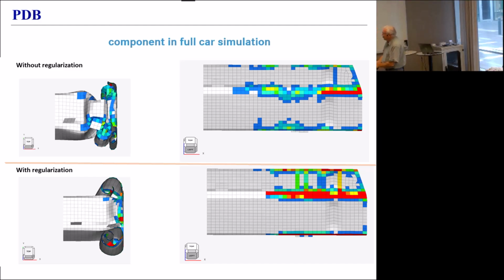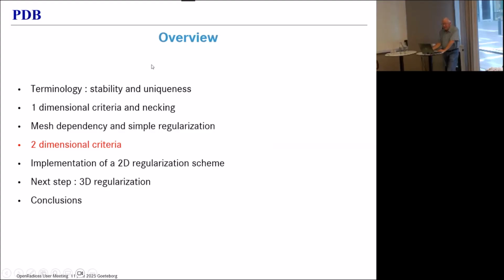And the reason for that is that we had a failure model there calibrated for a 1 millimeter mesh. In the application, we had a 4 millimeter mesh. It was regularized based on uniaxial tension. You apply that regularization to a state of shear, and you fail way too early. You get a time bomb. So we're going to have to make our regularization stress state dependent. But for that, I'm going to have to know, when does localization start under biaxial loads, under shear loads? When does regularization start for a given value of the triaxiality?